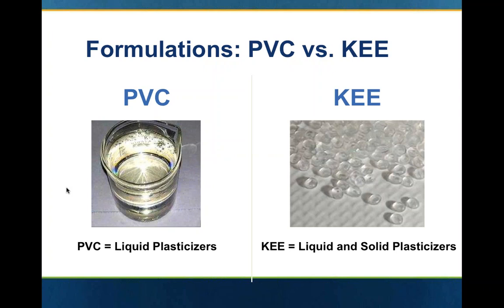Some of the old versions of PVC were very, very thin, and the plasticizers that were used were not very good, and the early versions of PVC were typically unreinforced. So they were thin, unreinforced, with not so good plasticizers. And what happened was, after exposure to UV, the plasticizer would actually leave the sheet and the product would become brittle over time.